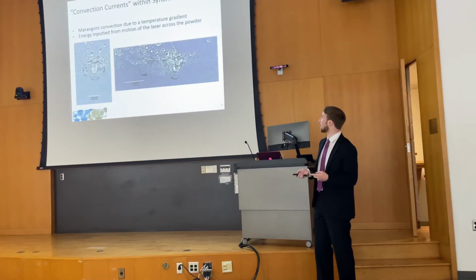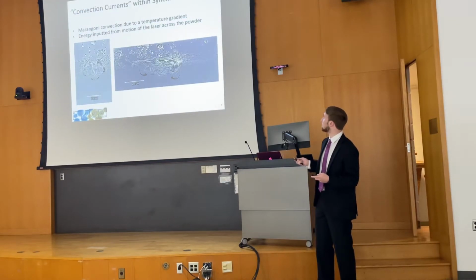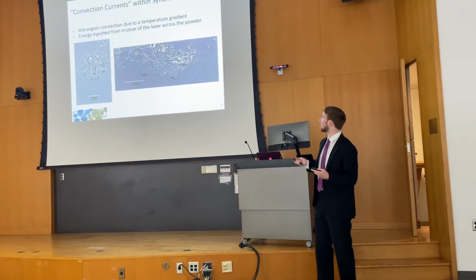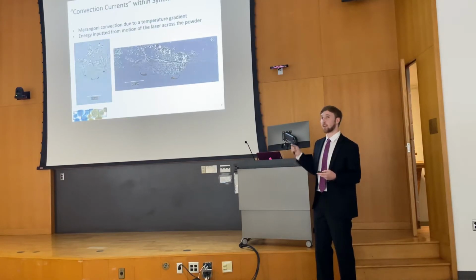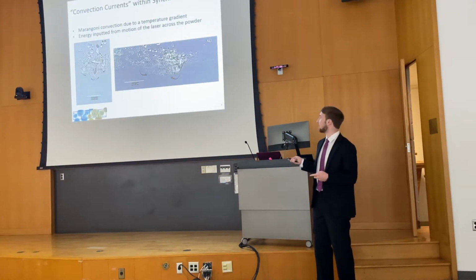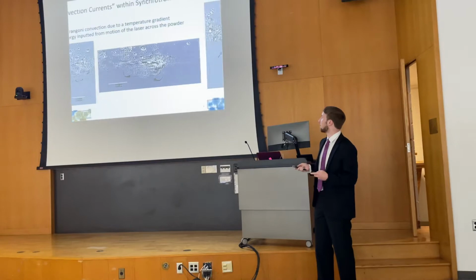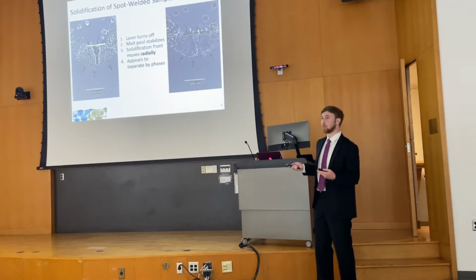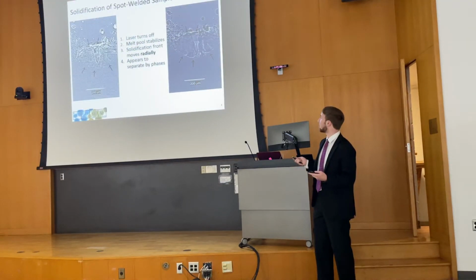The first thing I looked at was convection currents within the solidification. So Marangoni convection, due to the temperature gradient from a high-powered laser, caused a lot of fluid to flow within the melt pool. This energy inputted from the motion across the powder meant that it was moving even faster in the line scans relative to the spot welds. Next, I looked at the solidification of the spot weld and found that after the laser turns off, the solidification front moves radially inward and the melt pool stabilizes, and it appears to separate out slightly by phases.